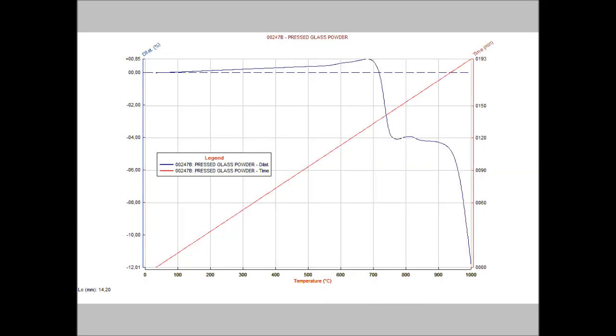This is a curve recorded on a sample of pressed powder of glass. The test continued up to the melting of the sample. We can clearly see that the material expanded up to 640 degrees and then it shrunk up to 4%. After that, it stays fairly stable up to 900 degrees, and above this temperature it starts collapsing. The test was ended when the temperature reached 1000 degrees and the shrinkage overcame 12%.